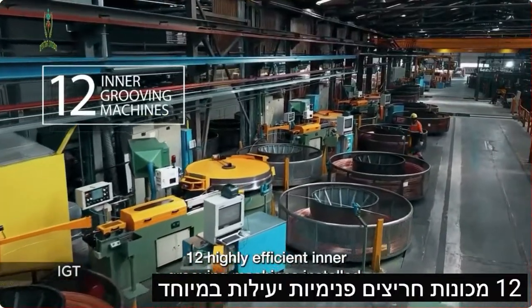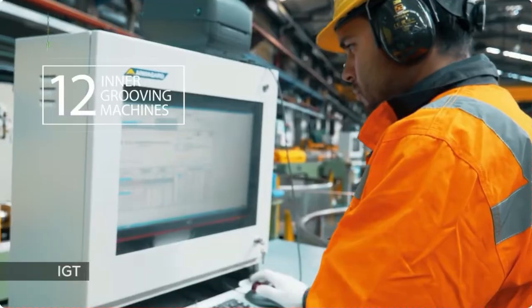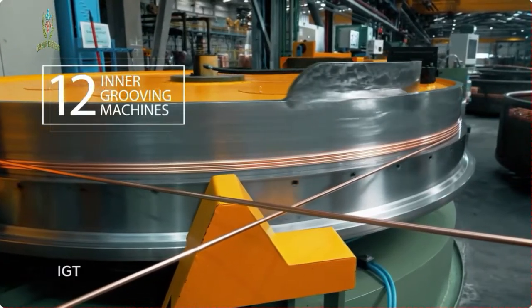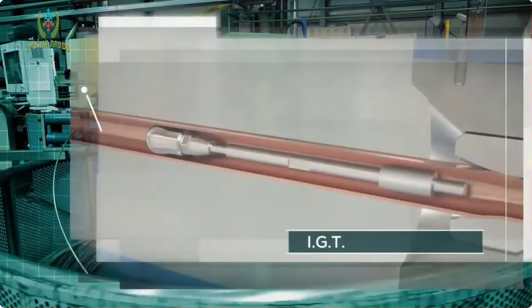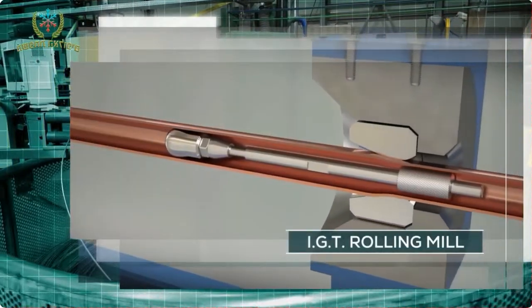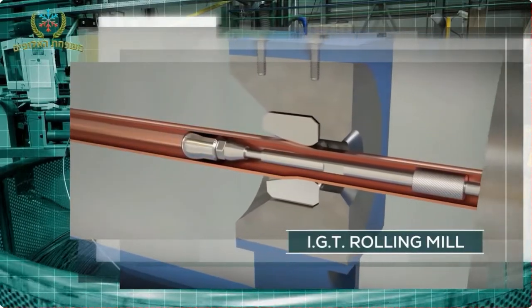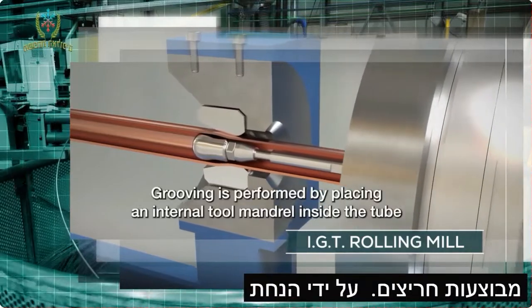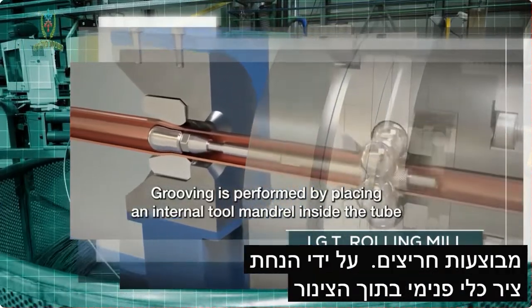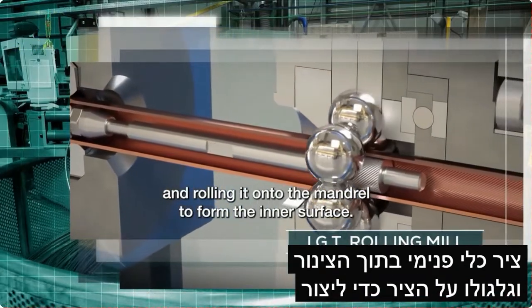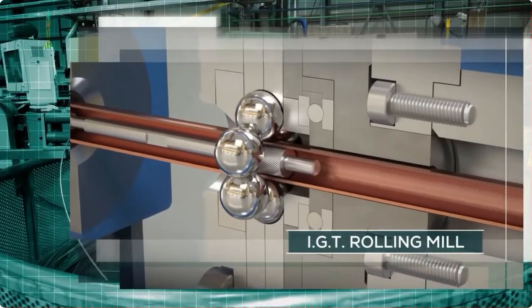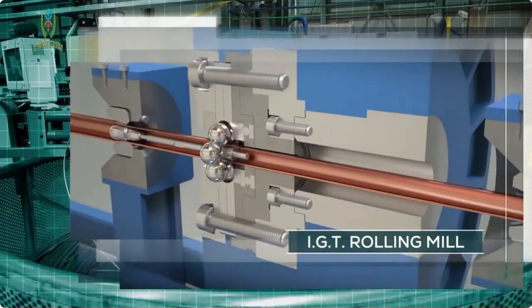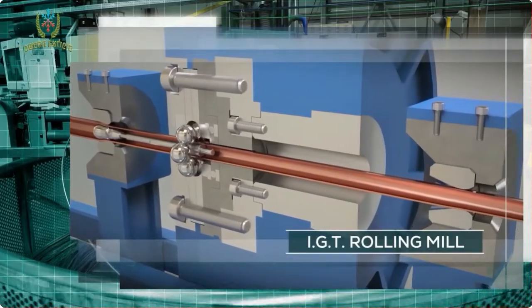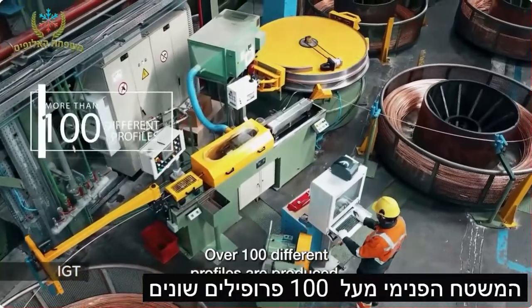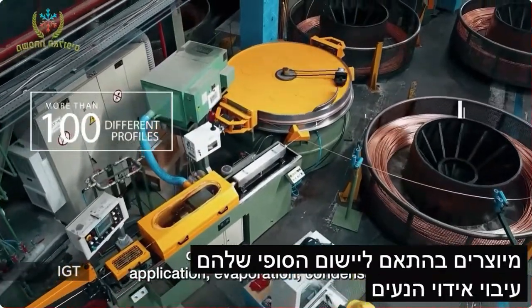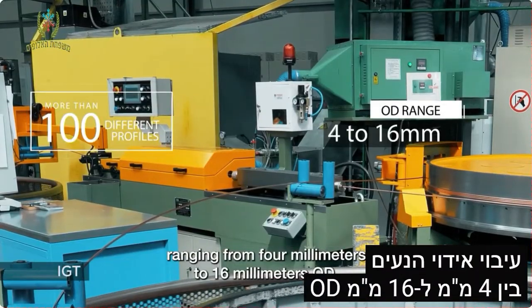12 highly efficient inner grooving machines are installed. Grooving is performed by placing an internal tool, a mandrel, inside the tube, and rolling it onto the mandrel, to form the inner surface. Over 100 different profiles are produced depending on their end application, evaporation or condensation, ranging from 4 mm to 16 mm OD.